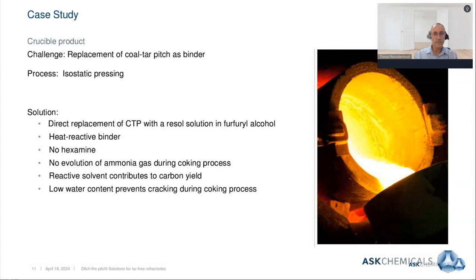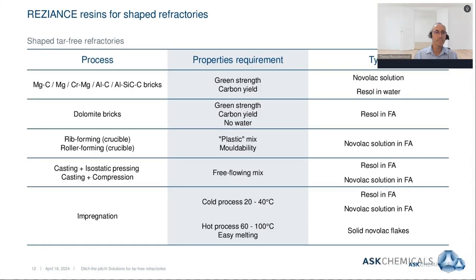We mentioned the reactive solvent being furfuryl alcohol, which may further contribute to carbon yield. And then lastly, the fact that we target very low water contents below 1% in our binder further lends itself to positive results in terms of quality in preventing cracking during the coking process. So here we have a very attractive, good example that works in practice. Next slide, please.